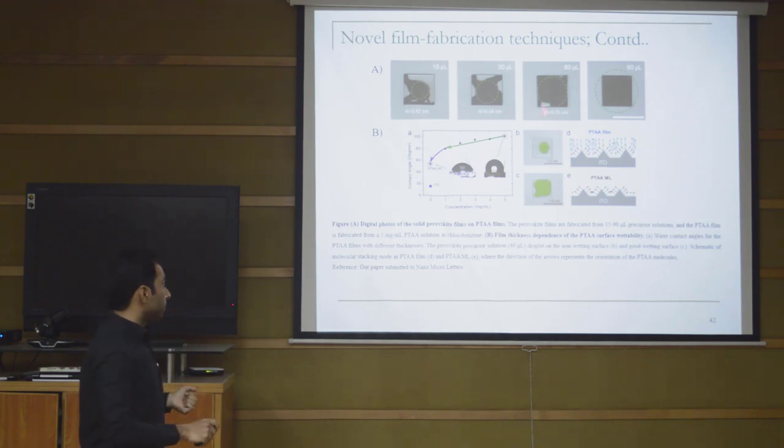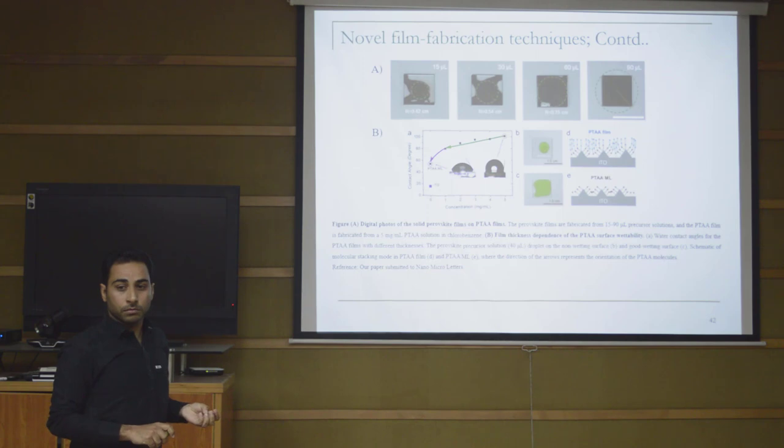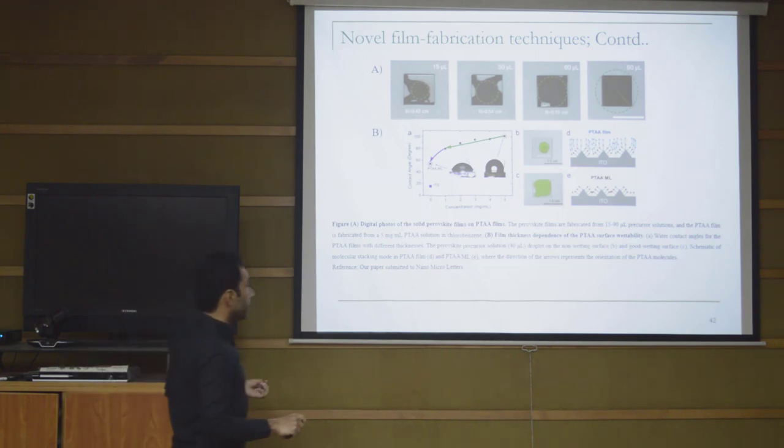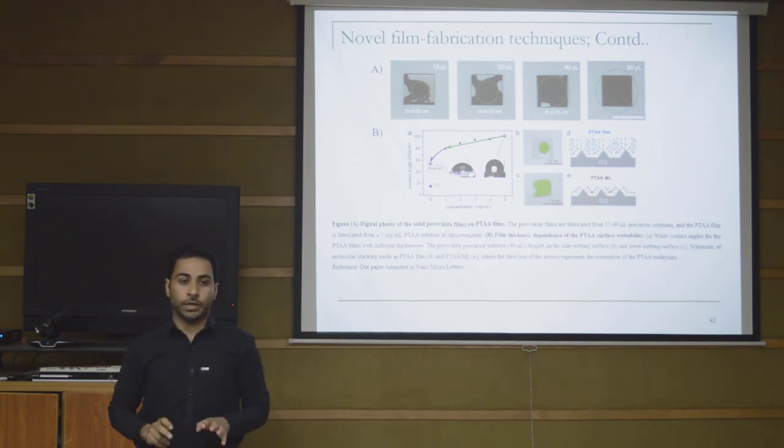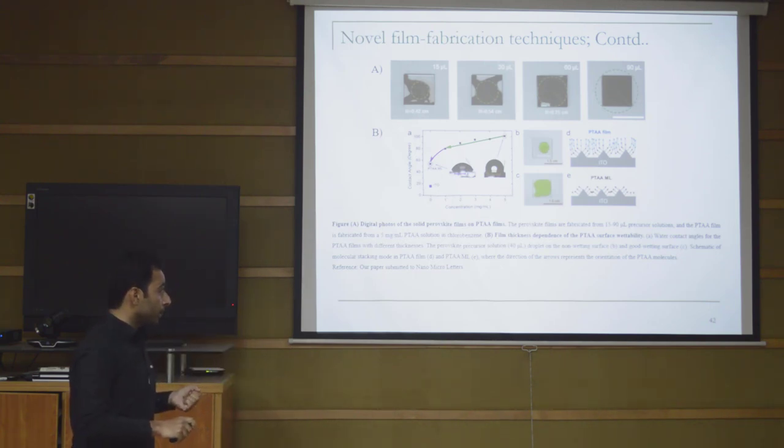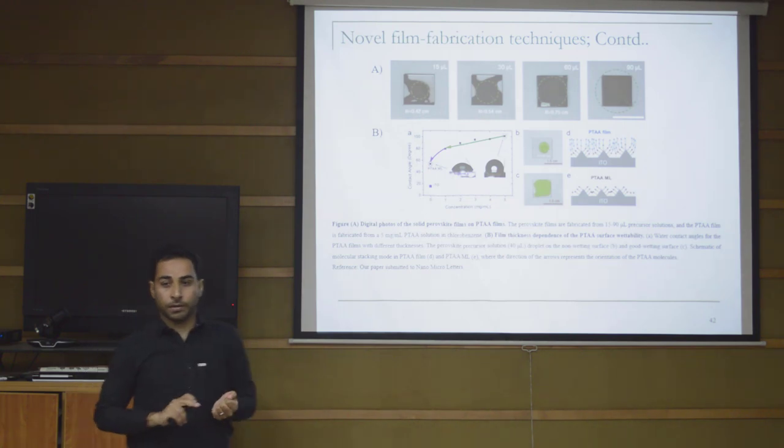Let me discuss why the precursor solution doesn't stick on the substrate surface. If you look at the bare ITO structure, the surface is very rough and solution sticks easily. But when you put the hole transporting layer, for example PEDOT, this film is very smooth and covers up the grooves and roughness of the ITO surface.